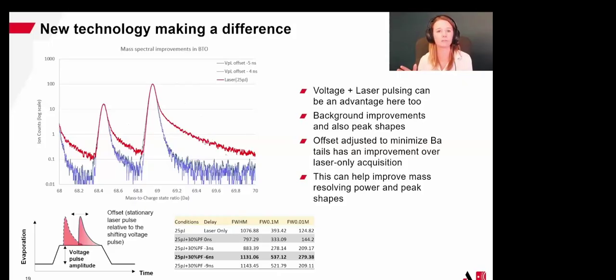This is the mass spectral peaks by using standard laser acquisition at 25 picojoules for this MLCC material. And if we choose a voltage plus laser, or simultaneous voltage pulse, with a 5 nanosecond offset of the voltage pulse relative to the laser pulse, one of the things that we can see is we can dramatically reduce the tail of our barium peak between 68 and 69 Daltons. And that gives us a major advantage of being able to make our peak sharper and look for elements that might be occurring in the tail of our barium or another peak.